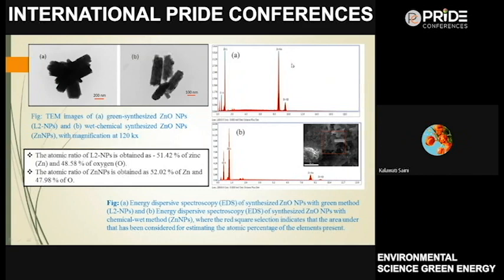These are the percentage composition of zinc and oxygen, or the EDS spectra of the synthesized nanoparticles. In the green synthesized nanoparticle, the zinc percent is 51.42% and oxygen 48.58%. And for the chemical wet method, the zinc percent is a little bit higher, 52.02%, and the oxygen is 47.98%.